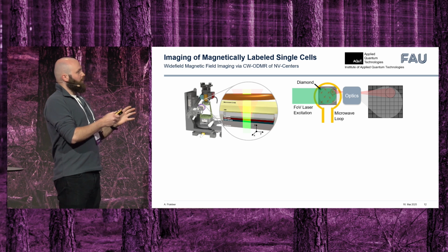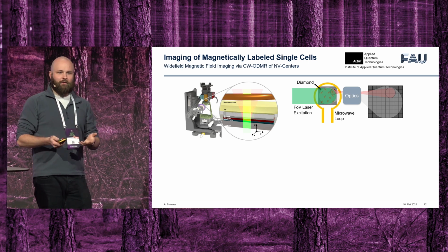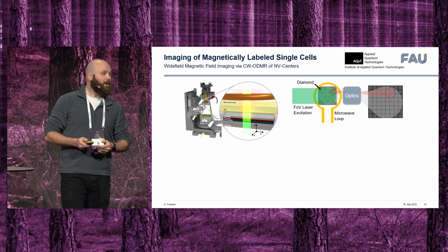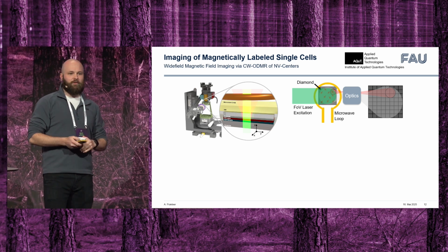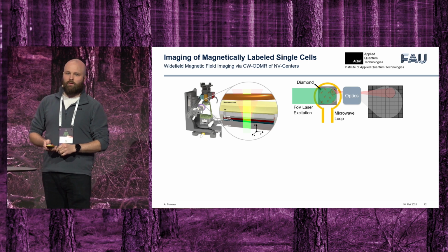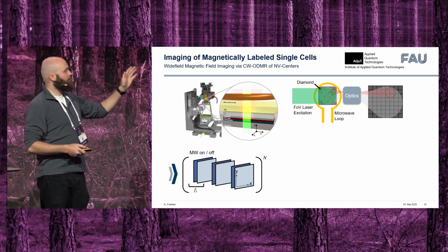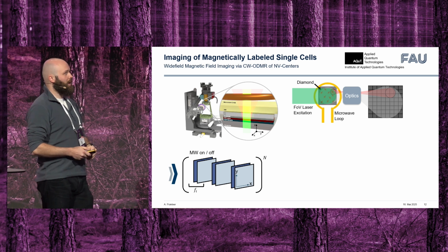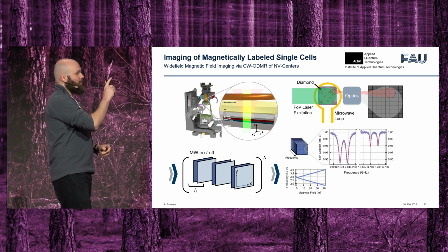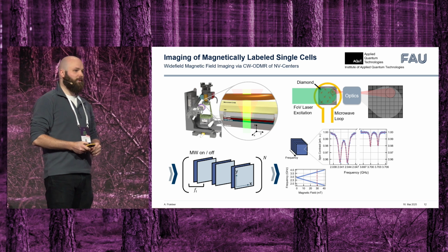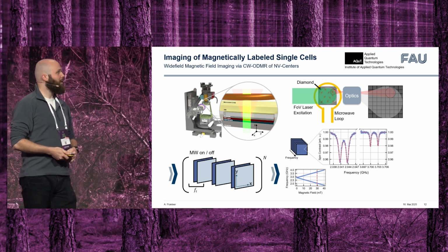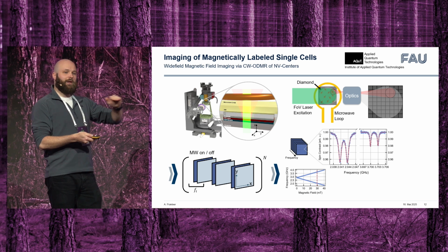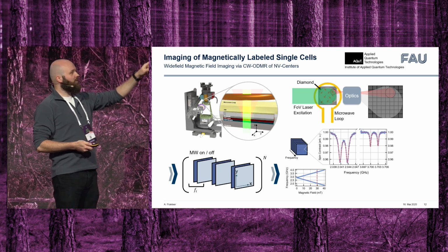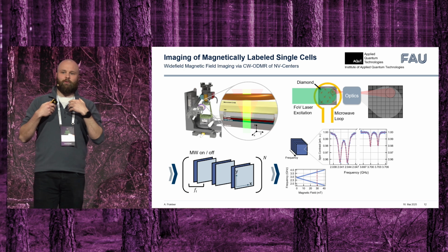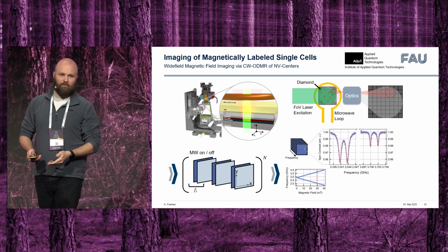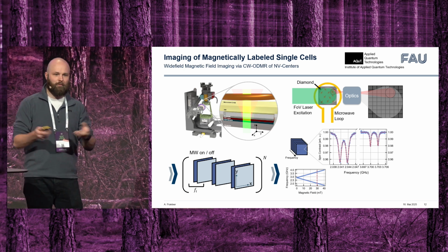Now, what we do is we take this microwave that interacts with the electron spin of the NV center, and we start sweeping it across the energy transitions of this electron spin state. And at each frequency, we take an image with our camera. And at some point, at some distinct frequencies, something beautiful happens, and this is where quantum mechanics comes into play. Due to these distinct energy levels within our spin system, we see certain frequencies where we can observe a drop in fluorescence. This is where basically our diamond goes dark. It's what we call a dark state.